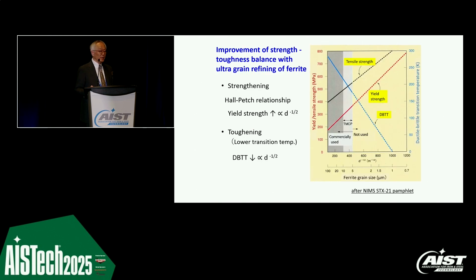For ultrafine grain, what is the importance of ultrafine grain of the ferritic steels? Of course we know strengthening can be obtained by the Hall-Petch relationship. And also toughening in terms of the ductile-brittle transition temperature, we can lower this transition temperature as a function of the grain size. So here is the plot of ferritic steel strength versus the grain size. And of course, as you decrease the grain size, we have an increase in yield strength and tensile strength. And transition temperature decreases like this.